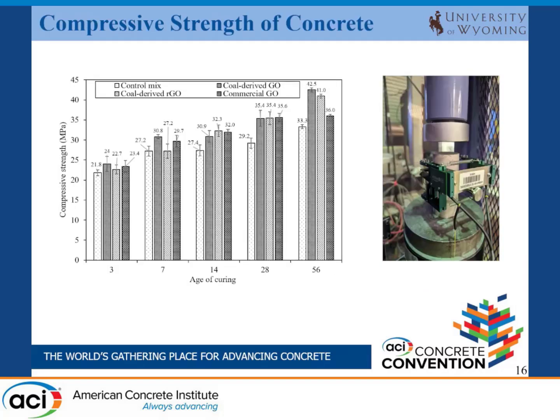The most impressive result we got was in the compressive strength. Till 28 days, we can see there is some increment of the compressive strength whenever we are using graphene oxide. But at 28 days, our graphene oxide and the commercial graphene oxide show approximately the same result. But at 56 days, our graphene oxide shows better results than the commercial one and the control mix. So if we do the percentage analysis, our graphene oxide at 42.5 megapascal is 20% higher than the commercial graphene oxide and 27% higher than the control mix.